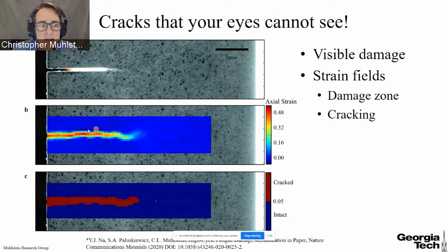The cool thing is that we can take this picture, we can compare one picture to the next as this crack is growing, and we can come up with a heat map of the strain distribution in the material. And we can mine this strain field to tell us where the damage is, and we can identify how long the crack is, and that's what's shown here in red. And the moment that we can identify where damage is and how it's growing, we can go back and close that all-important loop for the structure-processing-property relationship. We can explore what particular arrangement of fibers makes the paper strong or makes it weak.